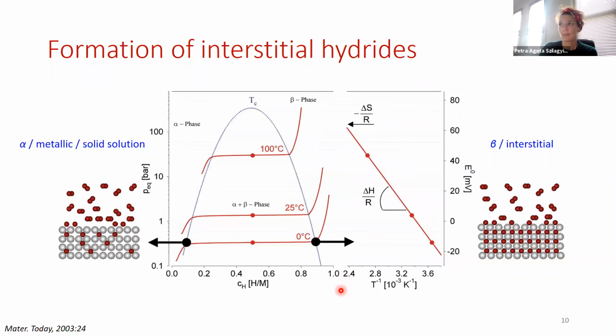So I would just like to say a couple of words about hydrogenation, just to disambiguate or clarify the terminology here. If you have palladium, it would be in the face-centered cubic phase. And if a hydrogen atmosphere is allowed on it, then the hydrogen molecules would be split into atoms, and the atoms would be able to diffuse into the bulk. And while the hydrogen pressure or concentration is low enough, this phase would remain. So this is the alpha, metallic, or solid solution phase. In fact, this tells you that it effectively behaves as a solid solution. So the physical properties of palladium remain the same.